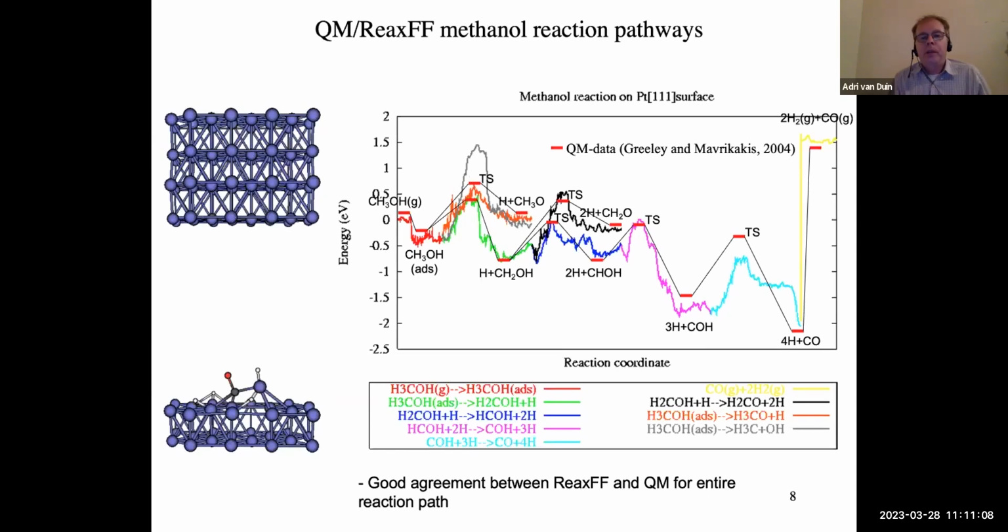And we can also look at competing reactions. A very important competing reaction is the dark gray curve over here. This is where we break the carbon-oxygen bonds. And that on platinum has a very high barrier. And that is why indeed platinum gets poisoned by carbon monoxide. And so we indeed have to mix platinum with other metals like ruthenium or nickel, so that we have hydroxyl groups available that can help in breaking the CO bond.